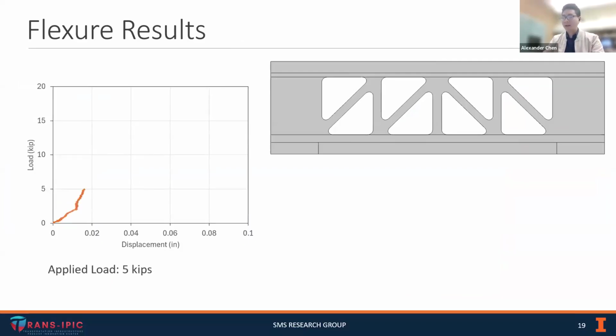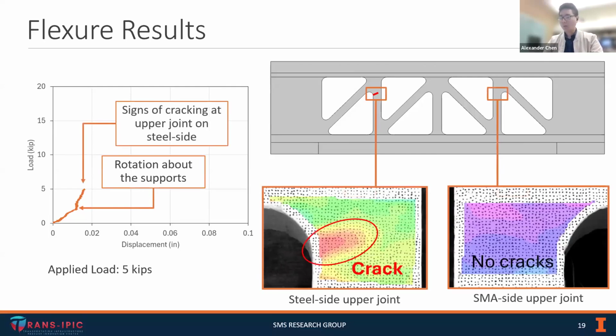So we began loading, and you'll notice that there is a slight change in stiffness. That was just due to rotation and a little bit of settlement at the supports. When we reached about 5 kips of applied load, by using digital image correlation, we detected cracks in the upper joint on this member that has steel reinforcement.